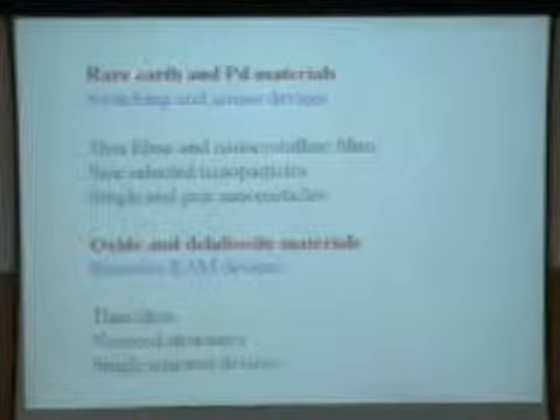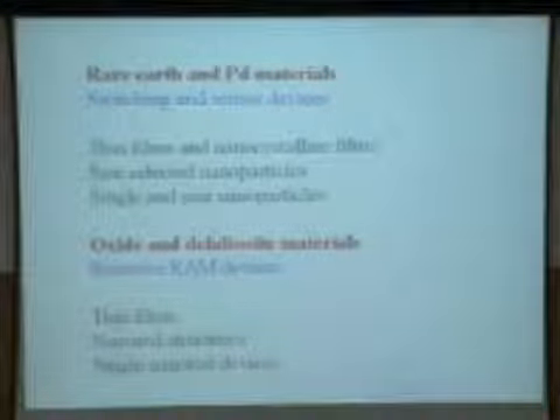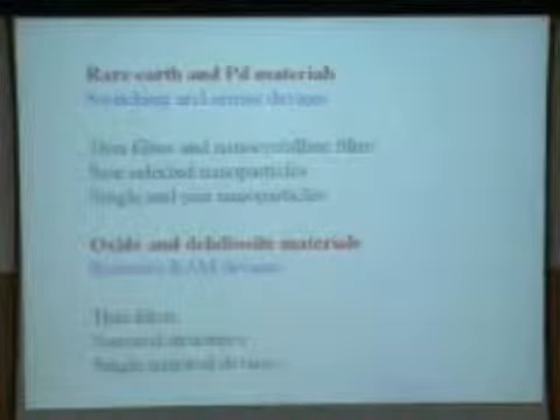You will see that when I discuss it, for certain applications we would like to make a pair of particles. One nanoparticle may be of a rare earth material and another particle of palladium, and we want to attach them together. So you can see that starting from thin films, nanocrystalline films, then size-selected nanoparticles controlling their size distribution, and then moving on to single and pair nanoparticles.